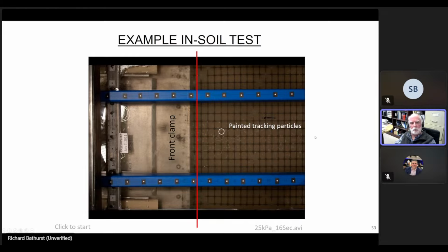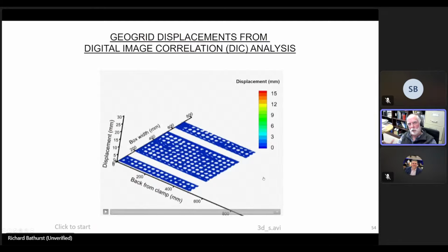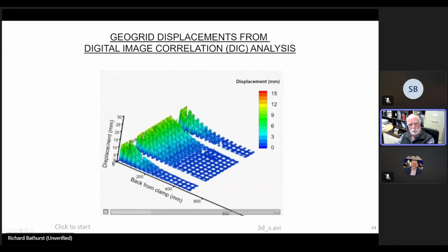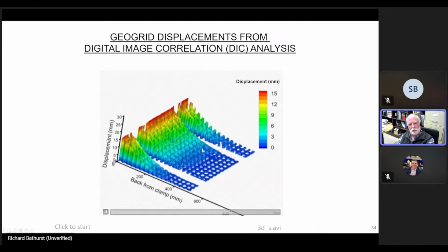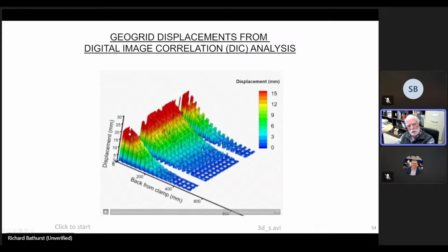And we can take that data because we can use DIC to digitize this data. What you're looking at here is the same specimen that you just saw in the previous movie. And as the test progresses, the reinforcement displacement at the front of the specimen is largest, and then the displacement diminishes as we move further to the back of the reinforcement. And at some point, you could argue around 400 millimeters back from the loading clamp, all of the load has been dispersed.